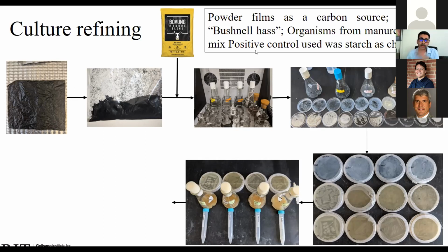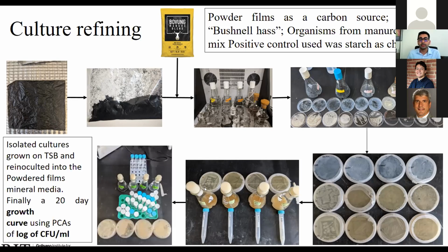We added some Bushnell-Haas media, which is the media which we originally used, which is nothing but a salt solution. And we again mixed the cells back up in the Bushnell-Haas media. We did this just to clean the cells up of any polysaccharides or any other nutrients stuck to the cells. We did this 2 or 3 times, so recentrifuging, cleaning, and recentrifuging, just to remove any nutrients or anything else. Finally, using the isolated and suspended cells, we re-inoculated our fresh Bushnell-Haas mineral media powder and powder mix. And at T0, we plated these.